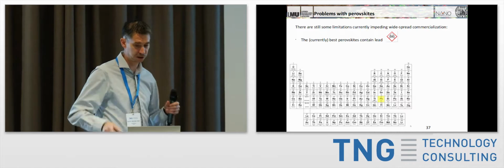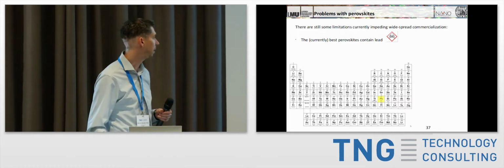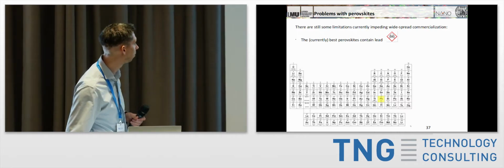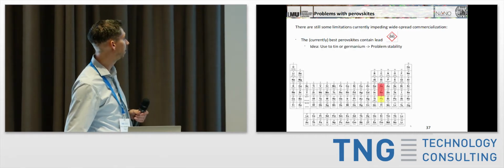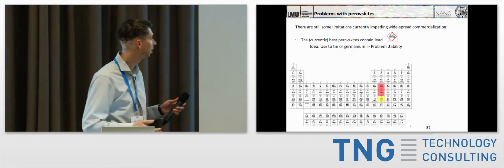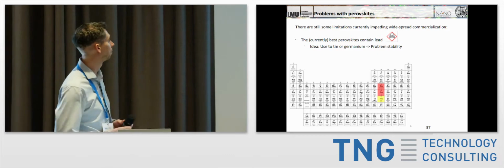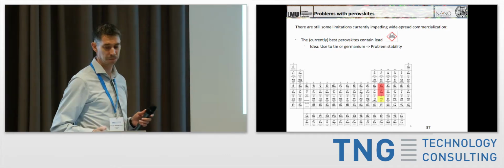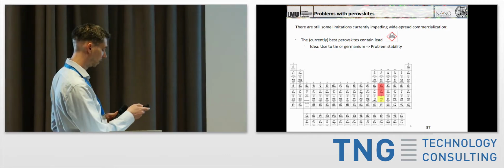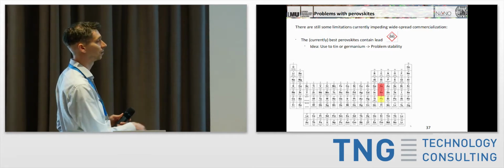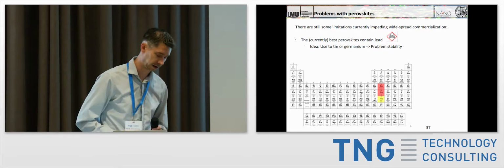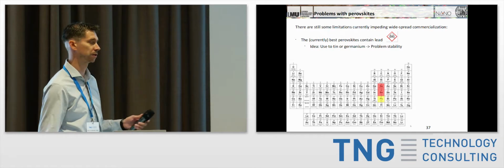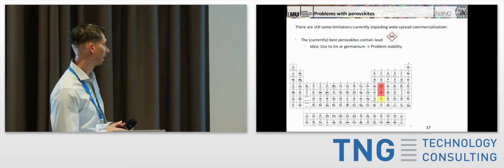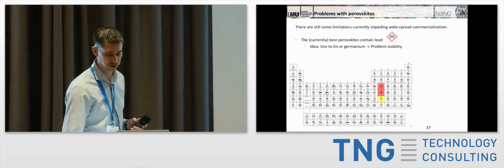So what people are trying to do to replace lead is to look at the periodic table. Okay, lead sits here, this yellow component over there. Why don't we stay in the same group and use tin or germanium, because they're chemically more or less the same. The problem is the stability, because tin and germanium like to form 4+ states instead of 2+ states, and they then act as traps for electrons and holes. So essentially once they're created, they tend to get lost and not be able to be used for electricity.